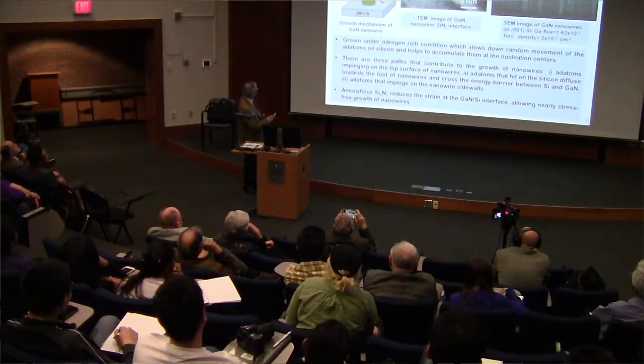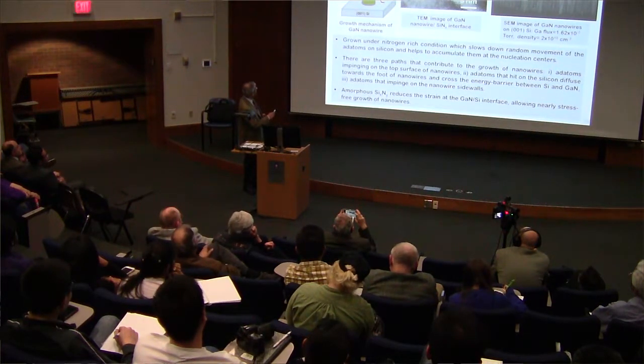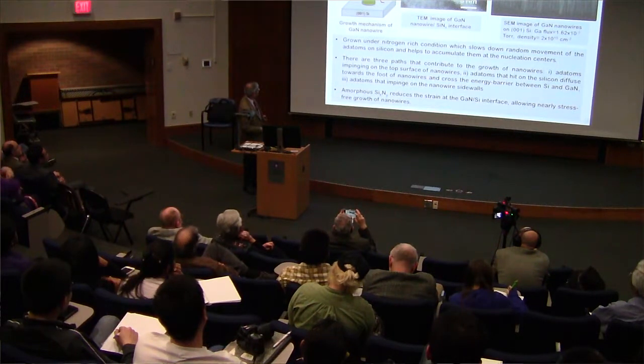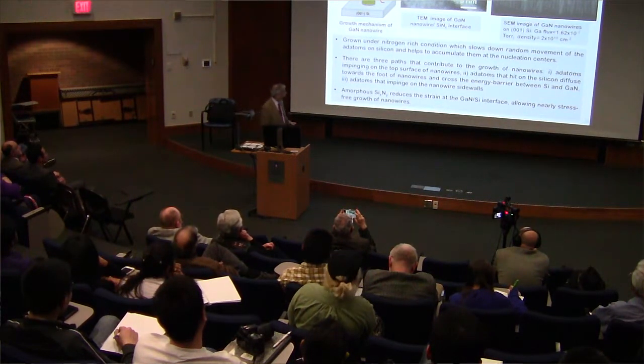Then the time-dependent stress on the silicon nitride layer forms the seed crystals of gallium nitride, and then the nanowires grow on those. This surface has the minimum energy, and so it grows on that. And again, as I always tell my students, most of the time nature is trying to help you. You just have to recognize it, and this is one of those instances.